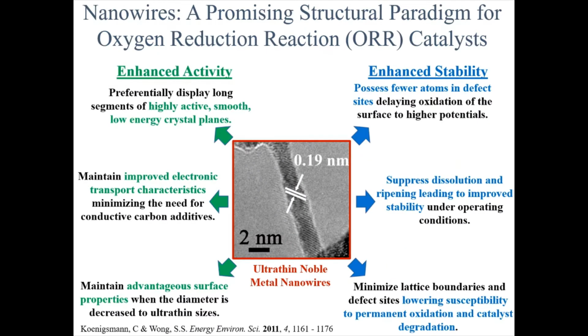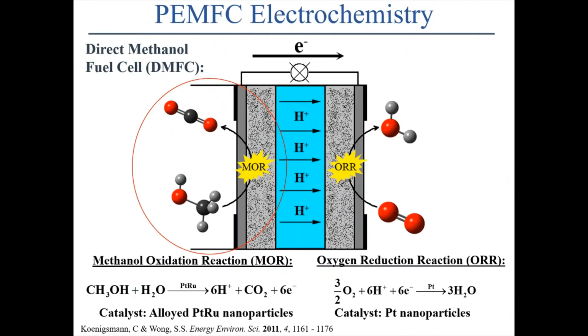So the reason why we focus on nanowires is because historically they've been shown to be both more active and more stable than other morphologies in terms of catalysis. And this has to do with the fact that they tend to display highly active smooth crystal planes, along with having improved transport characteristics. So that can lead to more efficient transport of electrons. And also they tend to have fewer defect sites, and they tend to be less susceptible to Ostwald ripening and other ripening processes that lead them to be both more active and more stable in the long run for the reduction of oxygen.